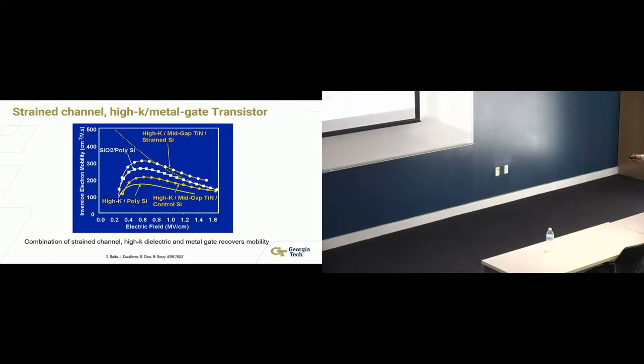But you could see that you can recover almost 50, 60% of that degradation. But then there was another knob that we already had at our disposal, which was the strain. We already knew how to engineer the strain from the silicon channel. So once you put that back together, high-k, mid-gap TiN, strained Si, then we could actually recover not only full mobility degradation, but actually you can provide that enhancement.